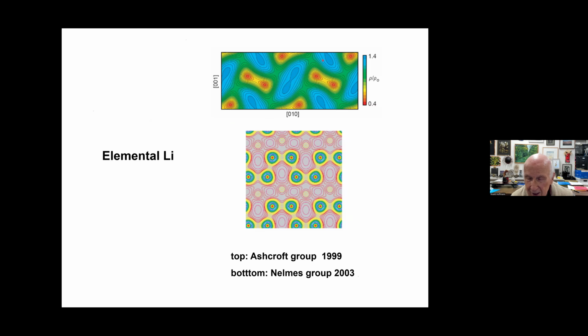The first suggestion of something, I want you to see how radical this suggestion was when it was made by Neil Ashcroft in 1999. He did it for elemental lithium, and he first predicted that lithium, which is, I think, BCC, but FCC is not far away, under atmospheric pressure, when you compress it, goes into a structure which you can see what it is. You can see 2 lithium atoms. And then there's a relative depletion of electron density. That's the yellow and red. And there is electron density in between the lithium molecules. So what it gives is a Li2 plus electron minus, a structure which I would call an electride, and which I knew from work of Jim Dye at Michigan, and I knew about electrides.